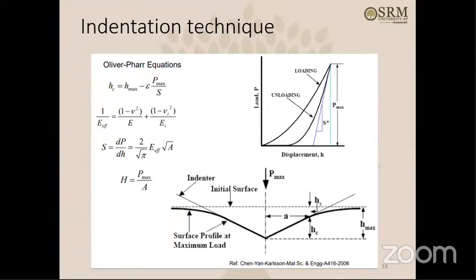Of course, it is beyond elastic. There is some plastic flow happening there. That's why, as you can see, the unloading curve is different from the loading curve. This is the unloading curve they follow, and from the unloading curve, they use this equation to get certain characteristics of the material.